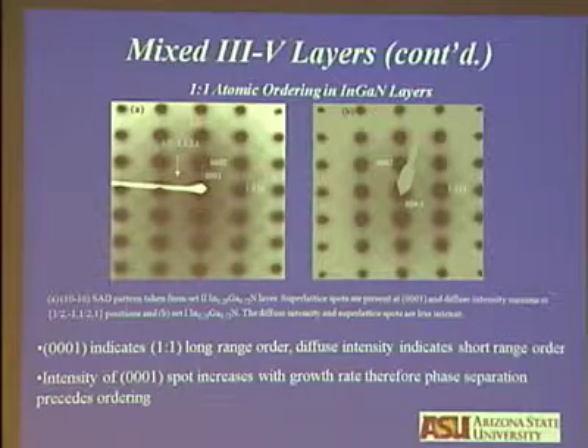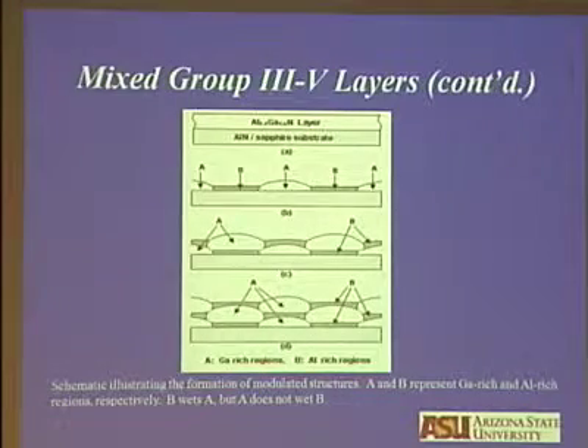This one is MBE. LPE of aluminum alloys is very difficult, as you know. And if you go back in history, aluminum gallium arsenide doesn't phase separate. But aluminum behaves as 2% smaller than gallium in the case of nitride. I'm not going to present any explanation, when Alex is sitting here, of why that happens. But this is a fact. Aluminum nitride lattice parameter is smaller than gallium nitride. So aluminum is behaving differently in the nitride than it does in the arsenide. And that leads to phase separation, the 2% size difference. You don't see phase separation in aluminum gallium arsenide. There are examples given, but they are unreliable.